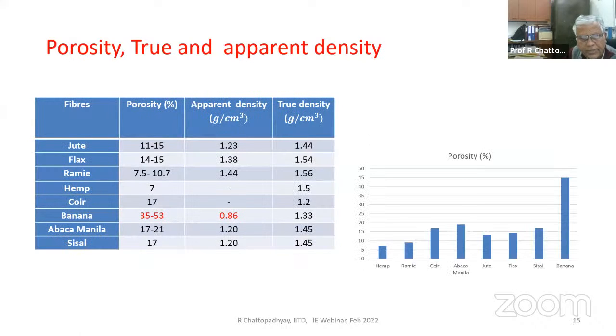Then porosity, as we have already seen, percentage-wise values are stated in this table. And therefore, their apparent density is also stated here, and the true densities are also given here. So the porous nature we have already seen by studying the constructions, and we can quantify the porosity, that is the pore volume percentage-wise, and in some fibers it can go as high as 35 to 53%, especially in banana fibers. So the porous nature of these fibers makes the fiber light, and this porous nature can also help in absorbing liquid within the void spaces of the fiber itself, besides the space that exists between the yarns.